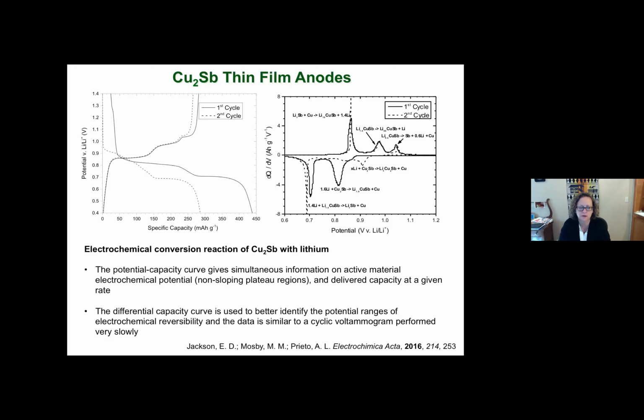And if we take that data and on the right plot the differential capacity plot as a function of potential, we can identify what those intermediates for each peak are, how they change as a function of not only cycle number, but also rate. We can identify what the stable stoichiometries are for the intermediates, and use all of this to understand really the kinetics of how this anode behaves under different charge rates.